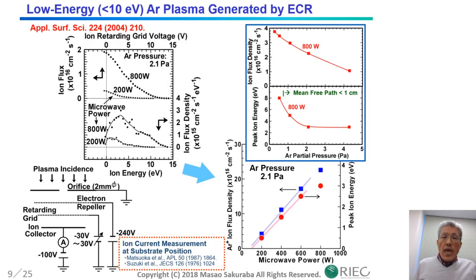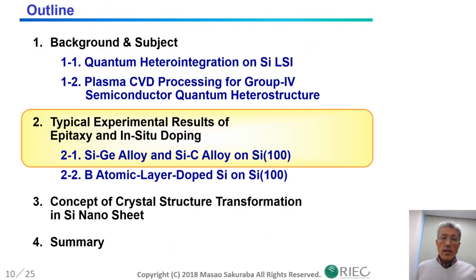In our apparatus, the actual argon ion energy distribution has been confirmed. The ion energy is suppressed below 10 eV. Moreover, by changing microwave power and argon pressure, we can control the peak energy. Next, recent advancement in low-energy argon plasma-enhanced epitaxy of silicon-based group 4 alloys on silicon substrate is shown.